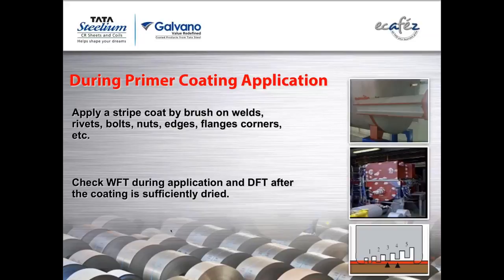Normally I have seen that the specification says, say, 100 microns of zinc rich epoxy primer, then 150 microns of micaceous iron oxide, popularly called MIO, and 40 to 50 microns of polyurethane. Now this top coat polyurethane is going to give you outdoor resistance. What we do is, the zinc is going to give us the benefit of cathodic protection or sacrificial coating, which we discussed in earlier slides.